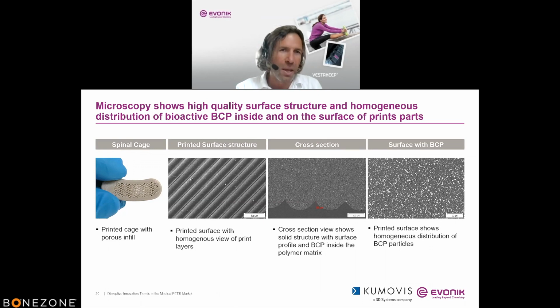And on these parts, you see on the left-hand side, you see very slightly that light goes through the cage, so it's really an open structure. And yeah, on the image, you see very nicely printed lines. So these are the, let's say, printing lines you see also on the cross section, and a very nice distribution of the BCP, which is enhanced in our PEEK with a very homogeneous surface.